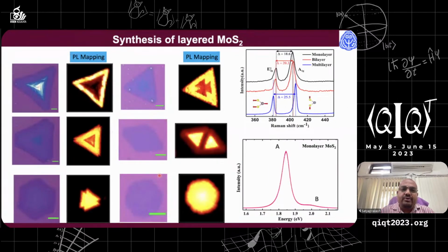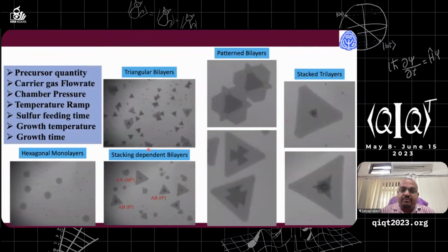Now, in our lab, we regularly synthesize monolayer MoS2, bilayer MoS2. These are some of the pictures that I'm showing you over here. And just by changing the carrier gas pressure, ramp temperature, and various other growth parameters, one can have different kinds of 2D material coming out of the synthesis process, which is very interesting as well.